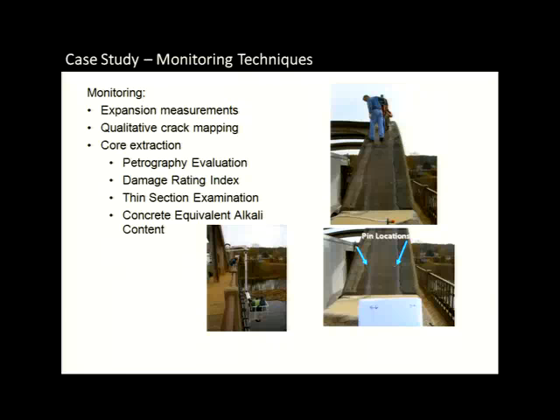So one of the ways that we monitor is that we embed stainless steel pins or stainless steel gauge studs into surfaces of the concrete. They embed typically anywhere from 1 to 3 inches, depending on how thick the concrete element is. They have a very small machined point at the end, and we use a comparator, basically a very fancy ruler, to go in and do hand measurements on the structure. A lot of times for historic structures, they don't want you to actually drill into the concrete and embed strain gauges. They want something that's a little bit less invasive and not going to affect the historical appearance. So that's one of the things that we do in this case.